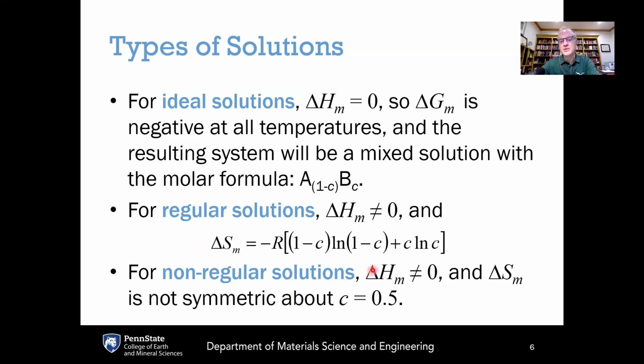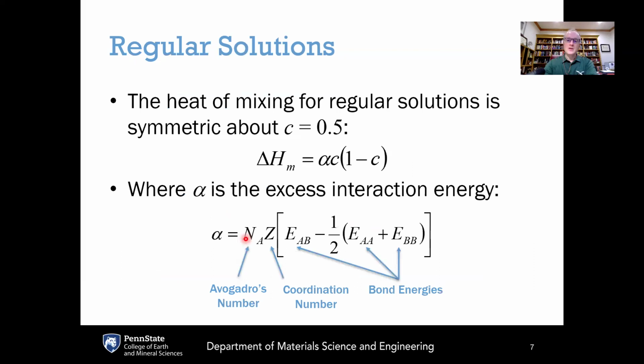With non-regular solutions, the enthalpy of mixing is non-zero, and the entropy of mixing is given by some more complicated formula. But for today, what we're going to deal with is regular solutions. So in this context of regular solutions, we can describe the heat of mixing, or this enthalpy of mixing, by a formula as shown here, which is symmetric about the molar fraction equal to 1/2.